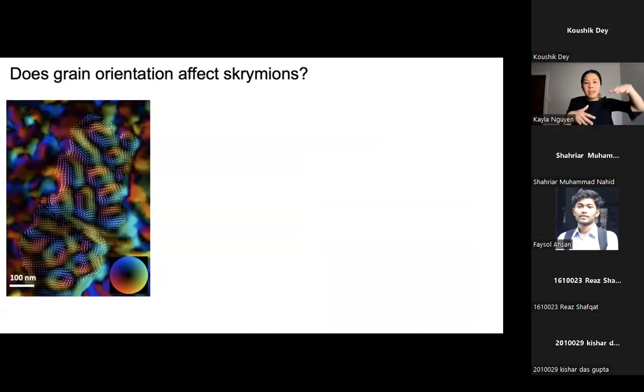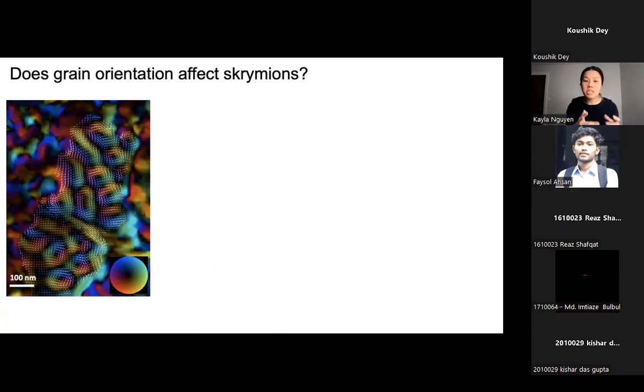So now, instead of having your ground state, which are these helical phases, so these squiggly lines, you apply a small magnetic field to your material. And because of the Dzyaloshinskii-Moriya interaction, your helical phases start curling. And when it starts curling, you form these magnetic skyrmions. If you look at this magnetic skyrmion structure, you can see that the top grain here has skyrmions that are rotating counterclockwise. The bottom grain here has a skyrmion structure rotating clockwise.